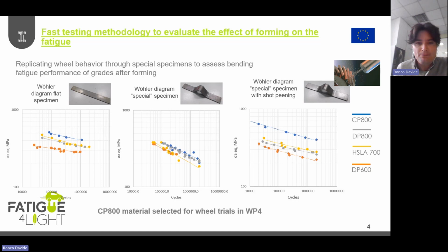Then we reproduced the fatigue test with this special specimen. This special specimen has two important things. The first is that it is bent, and so inside the specimen we also include the hardening phenomena that we have, for example, when we stamp the wheel. And also we convert the stress from pure traction and compression stress that we have in the flat specimen into a bending stress, that is what we have on the fatigue test on the wheel.